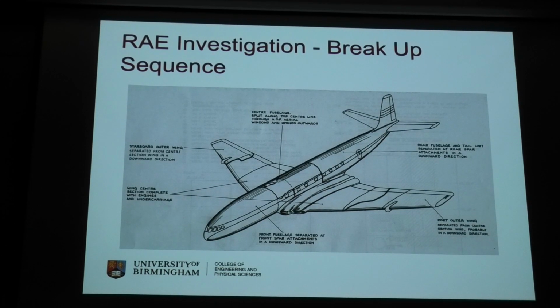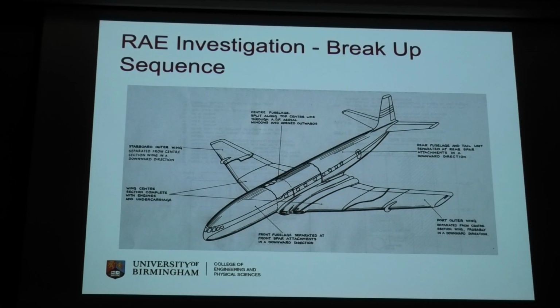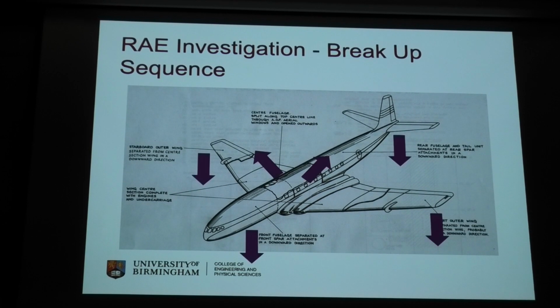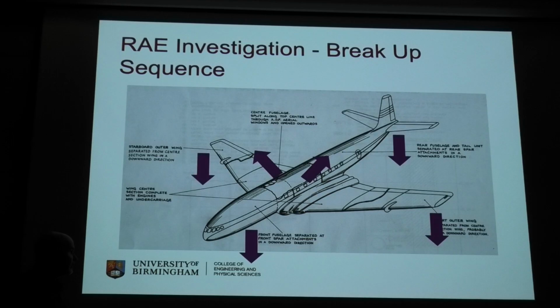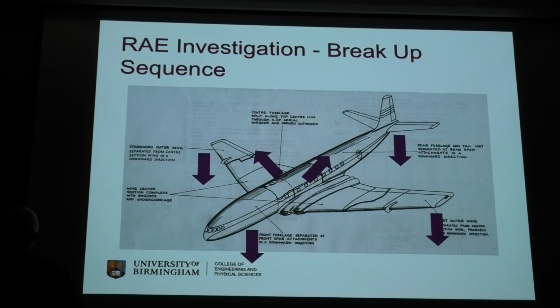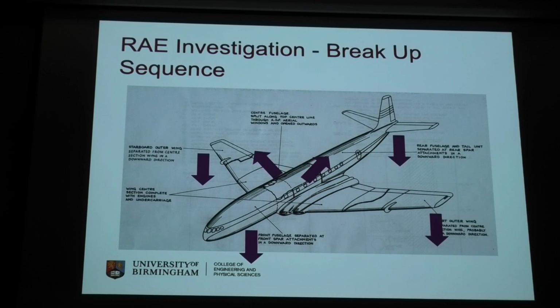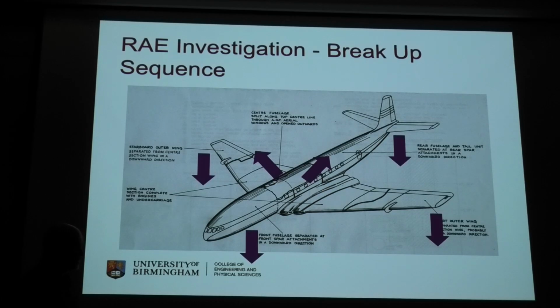What they did though find out was they worked out the breakup sequence, so that's the kind of the report. They knew that the first thing to happen was the top of the cabin split open, the top line broke apart and the two halves flew out. They knew that was pretty early on because they found some of the white cheat line from the Comet scraped across the wing surface before the wings broke. So they know that the wings then broke after the cabin had come out. They knew the tailplane came off after the internals of the cabin had come out, for example. And then the nose, tail both broke off, the wings split up, and that broke the integrity of the fuel tanks and they caught fire. So they worked out the sequence.